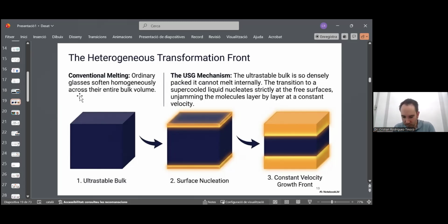Now, what happens if we do the same with an ultrastable glass? This glass that we have grown at 85% of the TG of the material, which has a higher density, larger devitrification temperature, and so on. Now we go above the devitrification temperature. The density of this material is so large, the mobility in the bulk is so small because of these efficiently packed molecules, that on the surface the mobility is higher. So on the surface, the transformation will start sooner, okay?